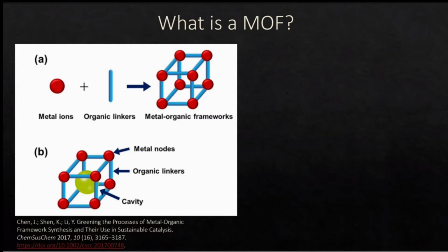We can see in this image that you have these metal circles that represent the metal ions and these blue bars that represent the organic linkers. When they come together, they make these porous structures that can be 2 or 3-dimensional. Whenever they're 3-dimensional, they create cavities, which can be functionalized by adding functional groups to those metals or to the linkers themselves. You can finely tune the size of the pore by using different sized linkers and the shape of the pore by choosing different metals. So there's a lot of fine tuning that can happen in these structures.